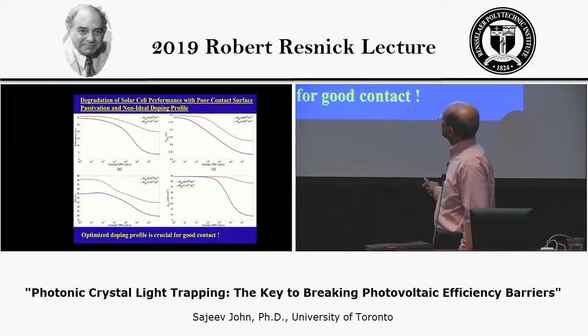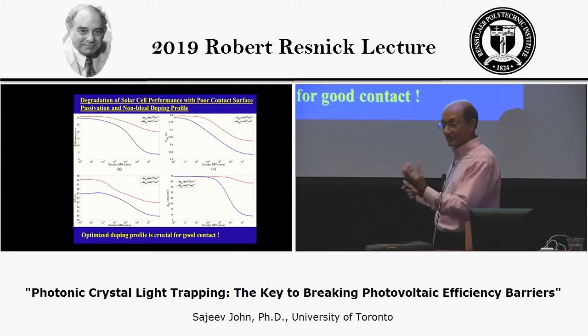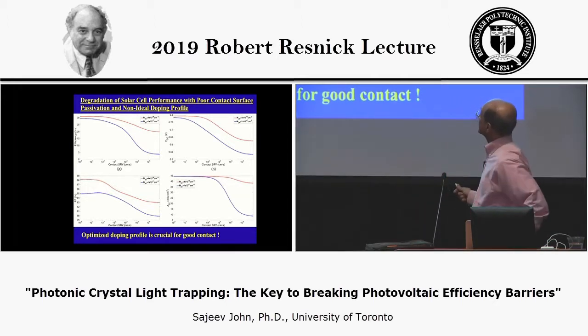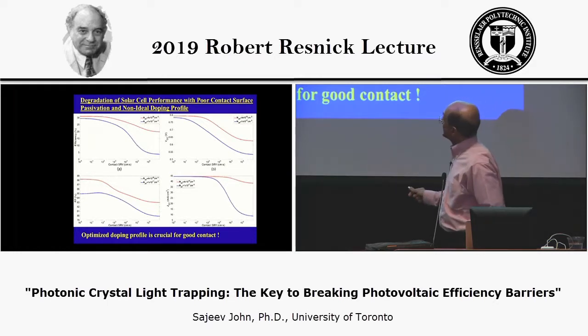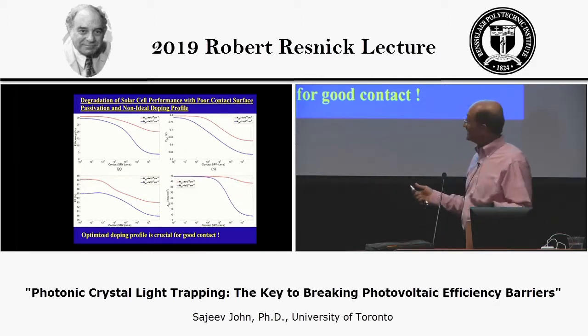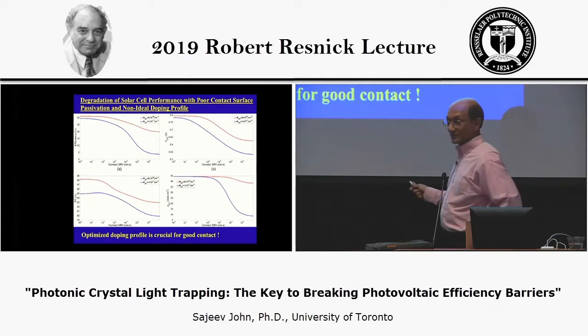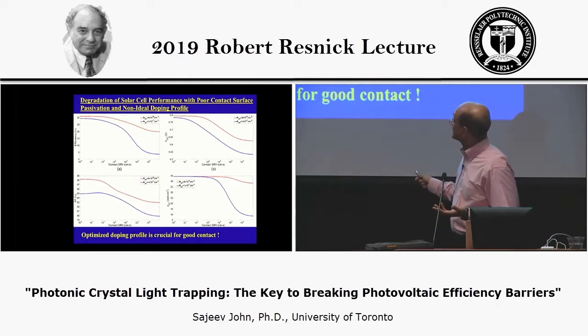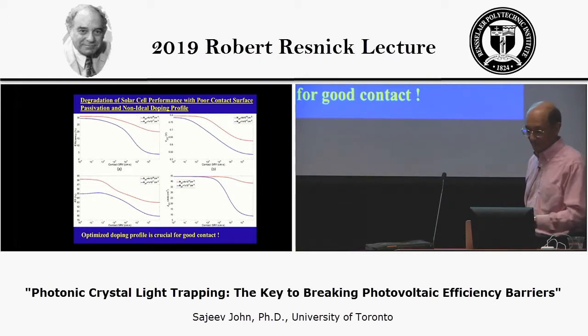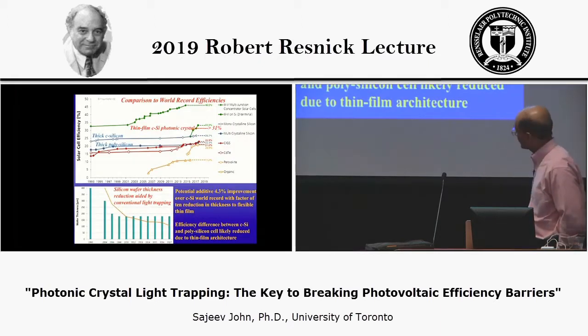And there are two cases that I plot here. One in which we have the optimum doping profile, which is this red curve. So you create a back surface field to deflect minority carriers, and if you don't do that optimally and go to a smaller doping profile, it becomes even more sensitive to this surface recombination velocity. So some amateur making a solar cell that hasn't passivated the surface very well could easily take our optimum inverted pyramid cell, which absorbs so much light, but still end up with a 5 or 10% efficiency. So the surface plays an enormously important role in achieving a very high efficiency here.